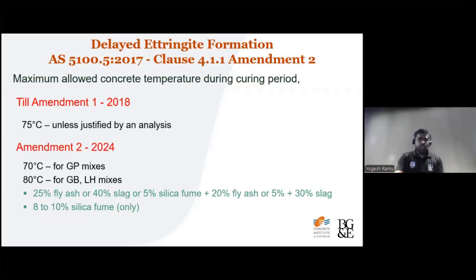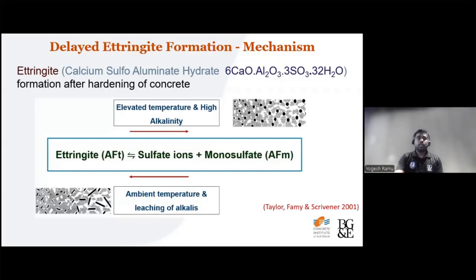To understand and make sense of these amendments, we have to know what ettringite is, what delayed ettringite formation is, first. Then we will talk through why this amendment makes logical and scientific sense. So what is ettringite first? Ettringite is one of the various hydrates forming in concrete. It's basically a calcium sulfoaluminate hydrate. And during the initial hydration phase of concrete, if it is precipitating, we call it primary ettringite.